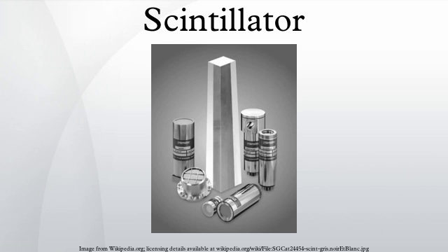Inorganic crystals. Inorganic scintillators are usually crystals grown in high-temperature furnaces, for example, alkali metal halides, often with a small amount of activator impurity. The most widely used is NaI(Tl). Other inorganic alkali halide crystals are CsI(Tl), CsI(Na), CsI pure, CsF, KI(Tl), LiI(Eu). Some non-alkali crystals include BaF2, CaF2(Eu), ZnS(Ag), CaWO4, CdWO4, YAG(Ce), GSO, LSO. Newly developed products include LaCl3(Ce), lanthanum chloride doped with cerium, as well as a cerium-doped lanthanum bromide, LaBr3(Ce).